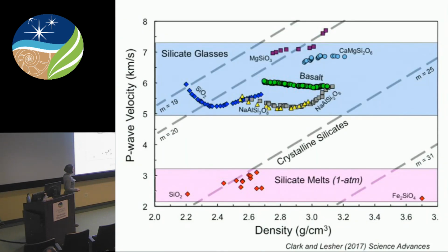So we're going back to our data for P-wave velocity as a function of density. At 1 atmosphere, remember, silicate melts have a very narrow velocity range. Similarly, glasses at high pressure have a very weak pressure dependence. What I'm proposing is that silicate melts, although they're not exactly glasses, are probably going to behave more like glasses than like crystals. So I take silicate melt velocities, their properties at 1 atmosphere, and apply the weak pressure dependence that we see in glasses at high pressure to the silicate melt data.